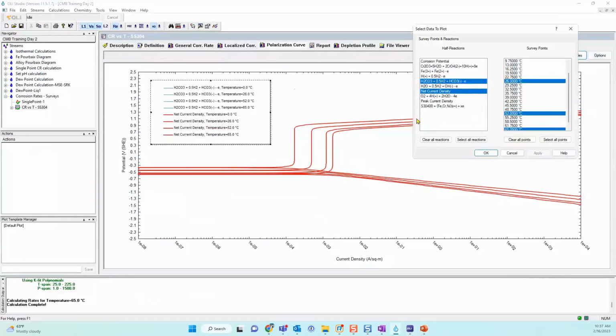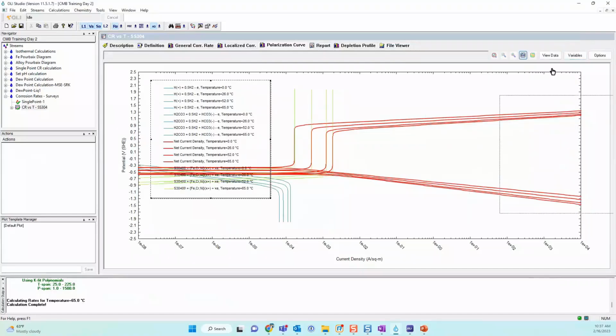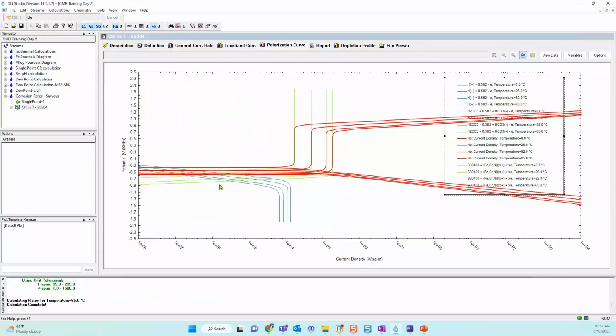This is weird. I don't understand. One second, please. Oh, maybe it's the proton. Yeah, it's the hydrogen. Okay, so yes, we are adding CO2. That CO2 is decreasing the pH of the solution, and the main reaction that is driving corrosion is that hydrogen reduction reaction that is happening on the surface for this stainless steel specifically.